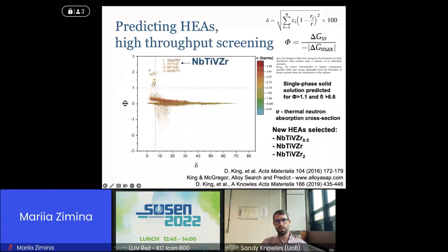And we were interested in both those that might be a single phase solid solution, as well as ones which might have a low thermal neutron cross-section. Particularly we were interested in these as potential fuel-clad materials. So we came across this system, niobium, titanium, vanadium, zirconium, and noticing that of those 4 elements, zirconium is probably the lowest neutron cross-section. We then did the derivatives, changing the zirconium concentration to change the neutron cross-section.